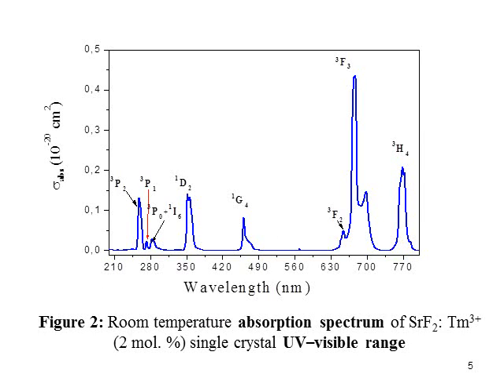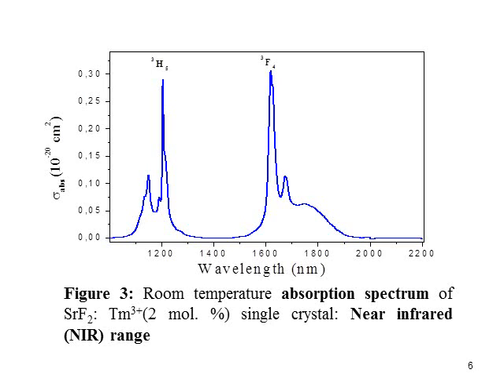The first optical measurement made on the studied sample is that we recorded an absorption spectrum which was calibrated in absorption cross-section over the UV visible and near-infrared wavelength range. In the first part of the spectrum, that is to say, in the UV visible part, the recorded spectrum is well structured and is formed of very distinct sharp lines. On the contrary, in the infrared part, there are 2 bands almost 400 nanometer wide in the extreme part of the spectrum.